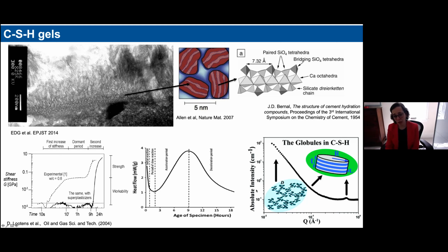This is small angle neutron scattering data from the hardened CSH, where you can see a signature of these nanoparticles. And then you can see the enhanced intensity at low Q, even when the material is completely hardened and basically homogeneous and very dense. So even when the material densifies and becomes as homogeneous as it can, there are still traces of this hierarchical organization of the structure that comes from this very complex aggregation that leads to the gel formation.